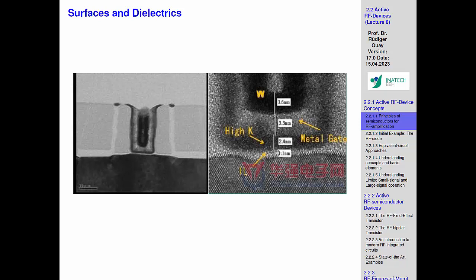And why can we see an atom? Because we are looking at it with an electron. So it's an STM, a scanning tunneling microscope. So we look with a much smaller wavelength than the nature, and then we can see the individual atoms. And here there's some silicon dioxide. By now, as I told you, the silicon dioxide in the most present MOSFETs has been replaced by another silicon dioxide type of material, which we call high K, because it has a higher dielectric constant, which we like. And here's the metal gate, but you can really see the atoms individually. So that's always important to remember.